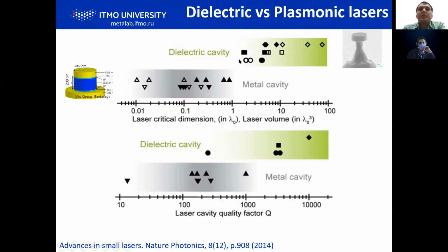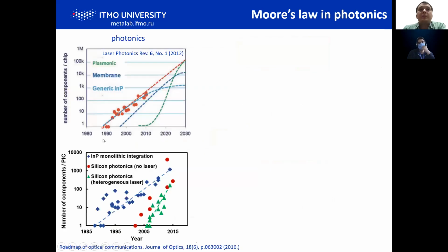These two families differ from each other due to the following parameters. For dielectric cavities, we have relatively low localization of light, but high quality factors for resonances. And vice versa, for plasmonics, we have very good, even sub-wavelength localization, but the price for this is low quality factors and high losses in the metal because of the higher imaginary part of the refractive index or dielectric permittivity of the metal. Compactization of lasers is important to compactize optical chips, and based on different technologies, the so-called Moore's law for photonics is in principle developing till now.